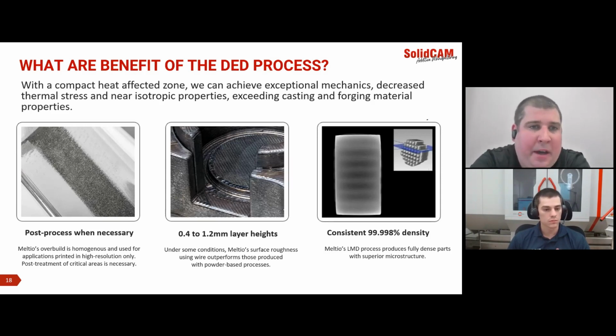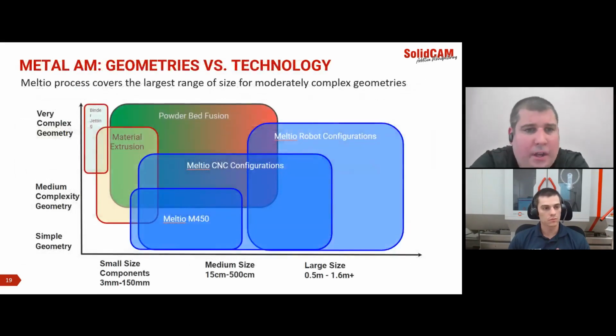Really reduces the amount of roughing time you may have with a conventional process compared to a hybrid one. Overall layer height, nominal is about 1 millimeter or 40 thousandths high. And we have extremely great density with the Meltio technology. So at 99.998% density, it really gives you great mechanical properties, overall exceeding cast properties when you compare to conventional castings. So move on to the next slide.